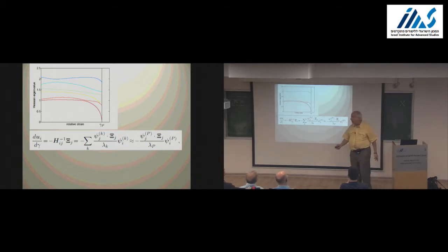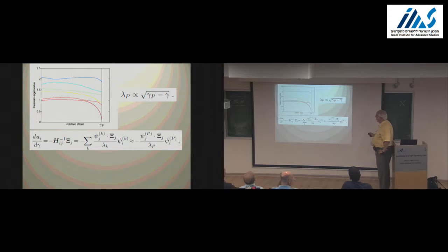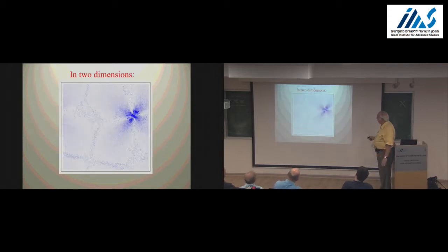Now, how do these eigenfunctions look? It's very interesting, because when you're at zero strain, all these eigenfunctions are delocalized. They're everywhere. But when you come close to a plastic instability, you can always show that the eigenvalue goes like a square root singularity, because it's a generic instability, a saddle node, one of the well-known catastrophes. When you do this, the eigenfunction localizes, and it localizes on what Allen and others like to call an STZ. An STZ is when some particles are moving out and some particles are moving in. This is the famous quadrupolar Eshelby thing that, not by amazing chance really, is equivalent to what Eshelby computed in the 50s for a sphere that you take out, squish into an ellipsoid, and push back. Same solution analytically.